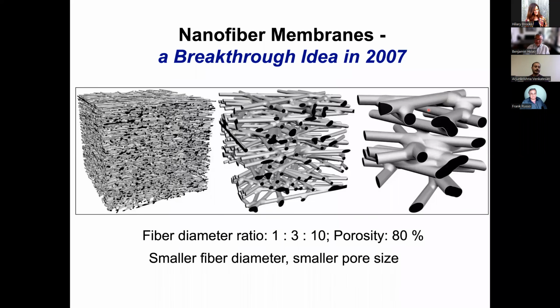We decided to just look at the non-woven format, the cheapest format that we can get. This is a simulation with 20% solid, 80% voids, porosity is 80%. If we have a way to divide this fiber diameter by a factor of 3, by a factor of 10, there's still 20% solid, 80% voids, then all of a sudden the pore size is much smaller. So if you take a section of this, it will be a very good coating layer.